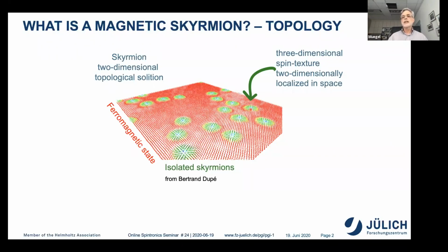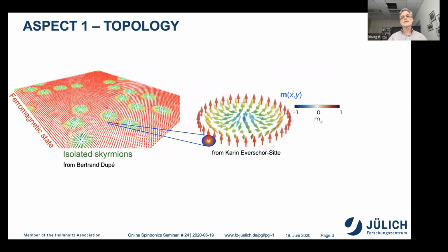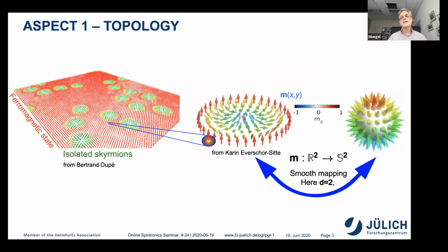Usually they are three-dimensional spin textures localized in a two-dimensional space, but these spin textures are not arbitrary. If you zoom into these worlds, you see, for example, that you have a winding magnetic texture, and if you look very carefully, you see that each magnetization direction appears exactly once and covers the entire surface of a sphere. So basically, we have a smooth mapping of the magnetic structure here, for example, by projection onto a sphere.